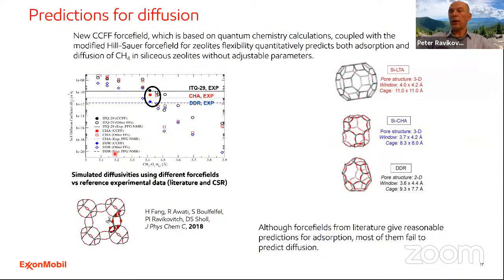What about diffusion? As I mentioned, when the size of the molecule approaches the size of the window through which this molecule diffuses, this system becomes very sensitive. And this is a very good example: diffusion of methane in a range of these 8-member ring zeolites, LTA, chabazite, and DDR. In these structures, the size of the window changes from 4 to 3.7 to 3.6 angstrom, and diffusivities for methane change by about an order of magnitude each step: 10⁻¹⁰, 10⁻¹¹, 10⁻¹².